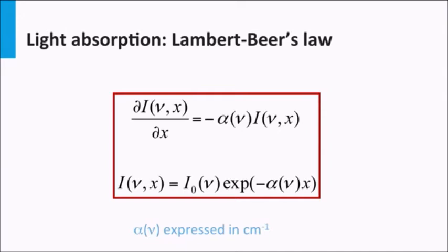Or presented in another way, over an infinitely small distance dx, the decrease in the light intensity due to absorption, dI/dx, is equal to the product of the absorption coefficient and the light intensity at position x. This is the differential form of the Lambert-Beer law. The Lambert-Beer law shows that the light intensity is decreasing exponentially in the x direction of the absorbing medium. It also means that at the side at which the light is entering the film, more light is absorbed in reference to the backside.